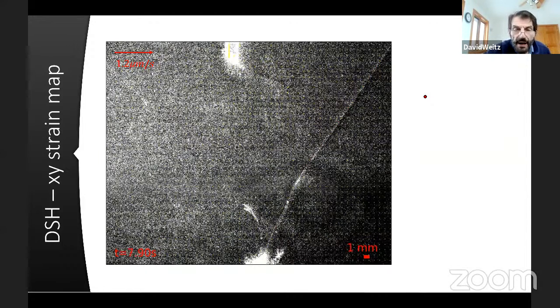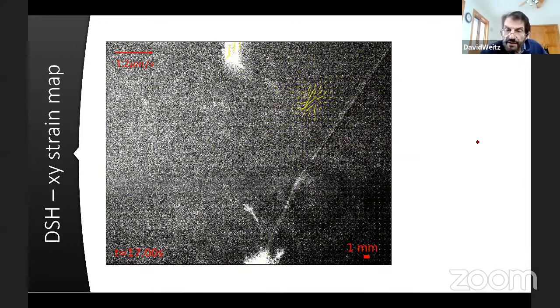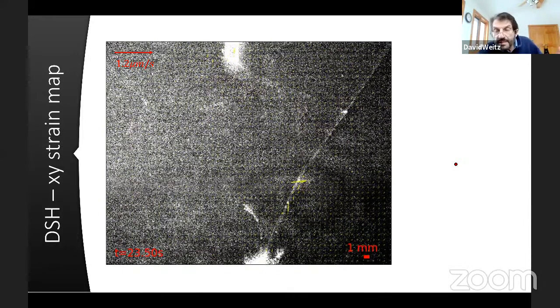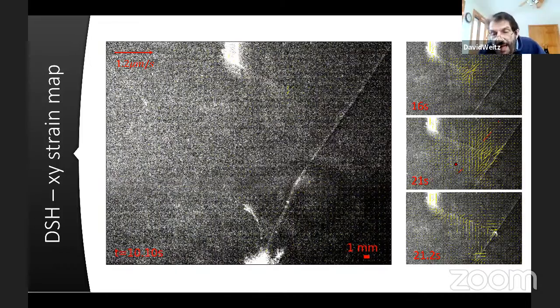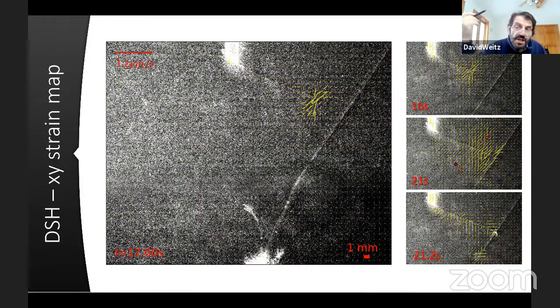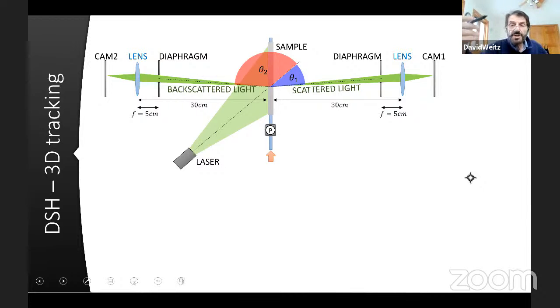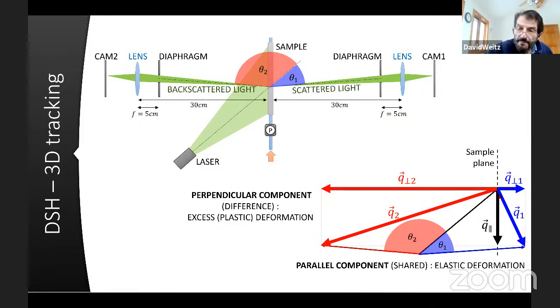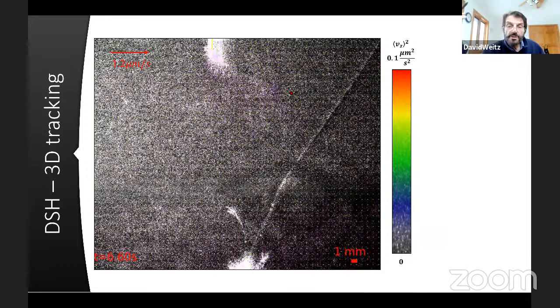I think some arrows begin to appear. This is the X and Y direction. And you can see now that you get a strain field far, far, far away from the crack. Again, it's a solid, it's being pulled away, but now the motion is tiny, but you can measure it because you're just doing this speckle holography. With some very clever adjustment, it's more complicated. Now you have to use two scattering measurements at the same time. By measuring the difference of two small wave vectors, you can actually measure something in the Z direction, the third direction. So now you actually have to make 4 measurements, but now you have a true three-dimensional motion.